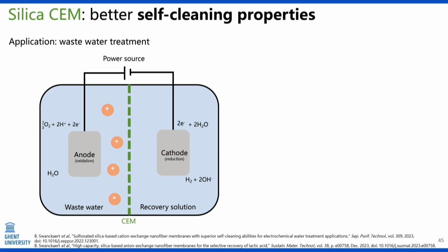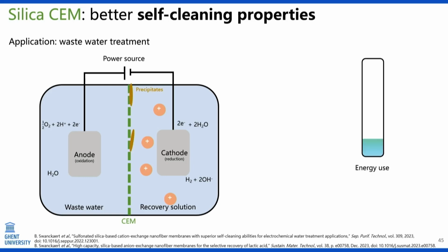And what we want is to extract, for a cationic membrane, the cations from the wastewater to the cathode. This is now done by other ion exchange membranes, non-nanofibrous based, and that works well, but a problem with most of these membranes is that we have a strong fouling. So after use, there's precipitation on the membrane, increasing the energy that you need to operate the membrane, and so after some time you need to stop the process, take out the membrane, clean it, give it a tedious cleaning treatment, load it in again, start everything all over again.